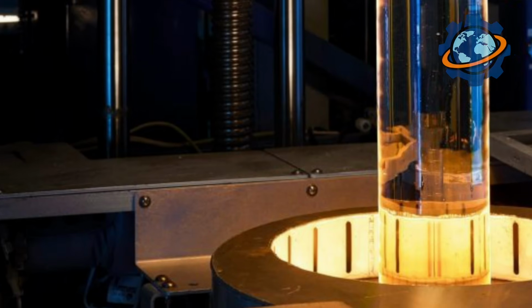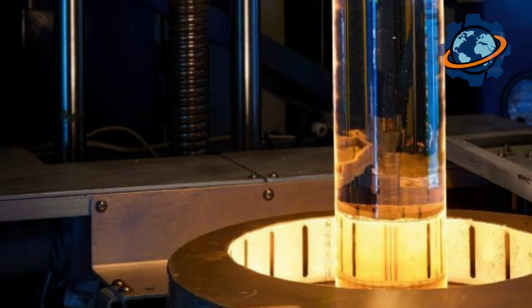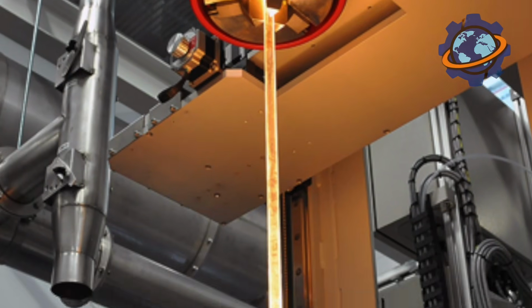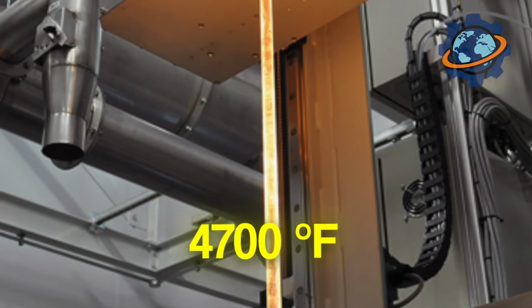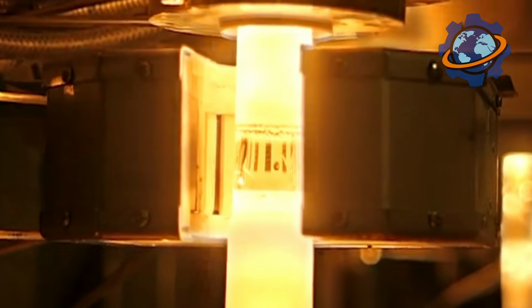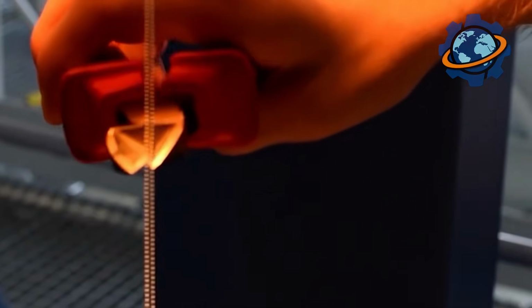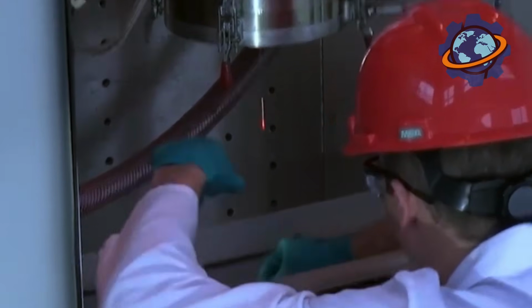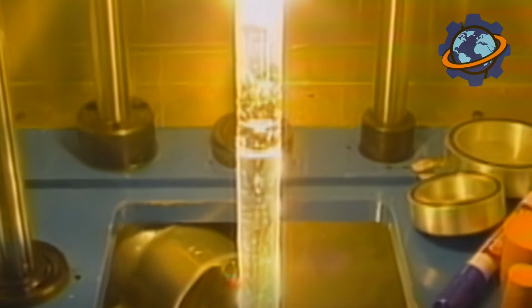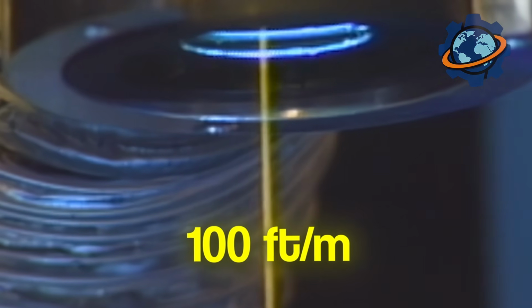The preform is placed in a special furnace that heats up very intensely. The temperature inside it reaches approximately 4,700 degrees Fahrenheit. This temperature is so high that the glass becomes soft and starts to melt, like caramel on a stove. When the end of the preform melts, a drop of molten glass begins to drip from it. This drop is very carefully drawn downwards, and a thin thread is formed from it. This thread, the optical fiber, is drawn at a speed of approximately 100 feet per minute.